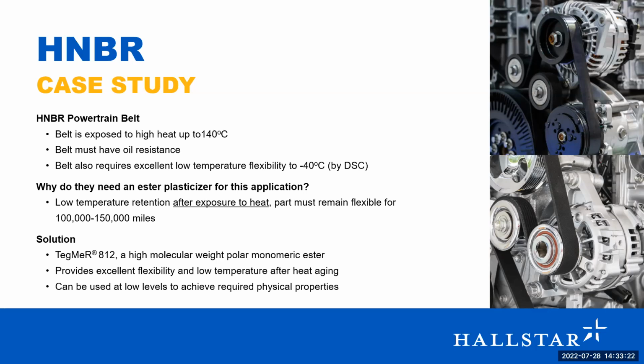So any monomeric ester chemistry, any phthalates that you would be able to put in there, may be compatible initially, but not after temperature. With some of these belts having to get 100,000 to 150,000 miles, in year 2 or 3 of owning the car, it might see extreme heat under the hood. And after 10, 20 years, you need to be sure that that belt isn't going to tear and it's going to be able to maintain that -40 C flexibility. So when you have a very cold day here in Chicago, your belt's not going to break right away when